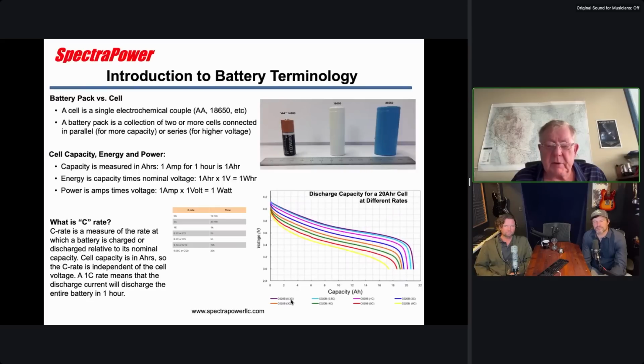So 0.5 C, which is a low rate, and going up to, I think the highest is 6 C, which means you're discharging it in about 10 minutes. Whereas at 0.5 C, you're discharging it in 2 hours. So this has a big impact on lithium-ion batteries. And you can see the difference: at 0.5 C, you get much more energy than you do if you discharge at a really high rate, like 6 C.